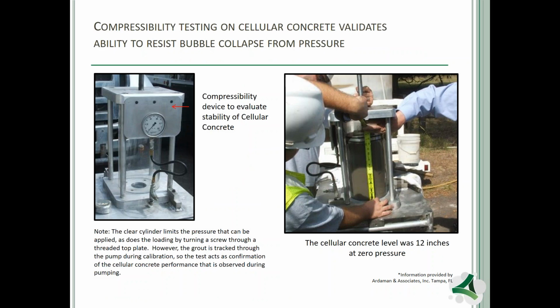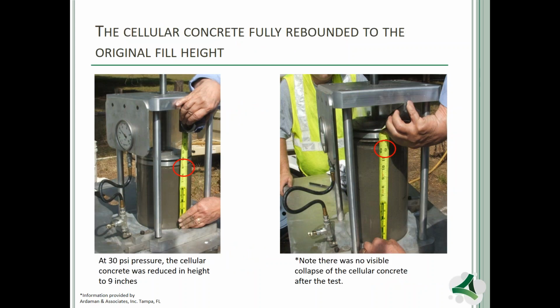I need to talk a little bit about bubble structure because of some of the things that we are doing with the bubbles today. We had Ardaman & Associates do a study where we filled a clear cylinder with a very fresh cement water foam mixture. We filled it up to 12 inches, put it under some pressure, compressed that material down to 9 inches, held it there for a short period of time, and then released it. Upon its release, it bounced back to its original 12 inches.